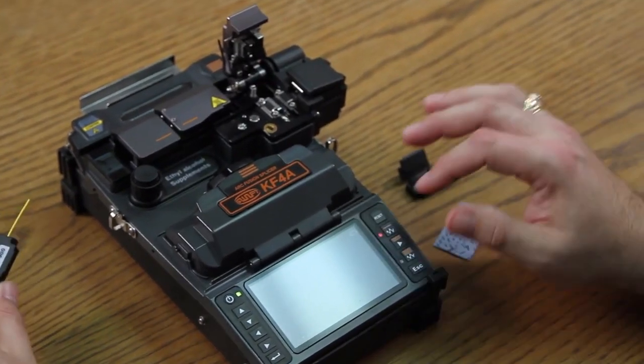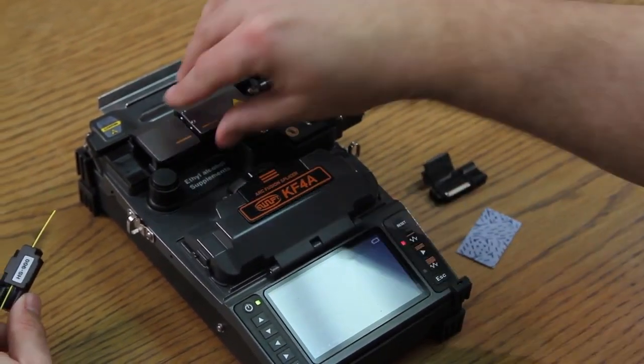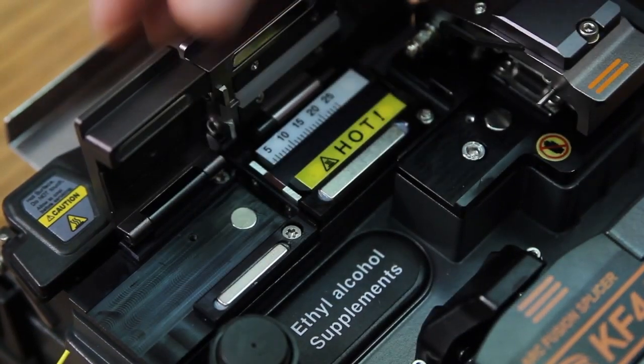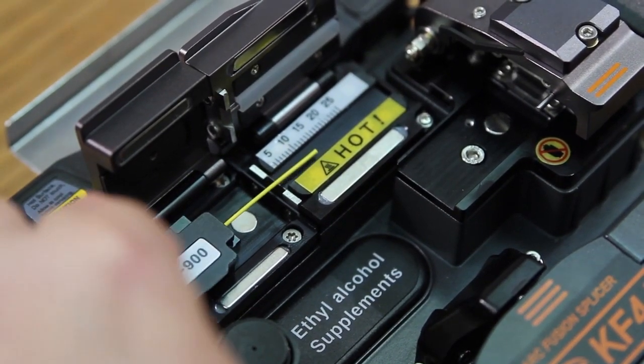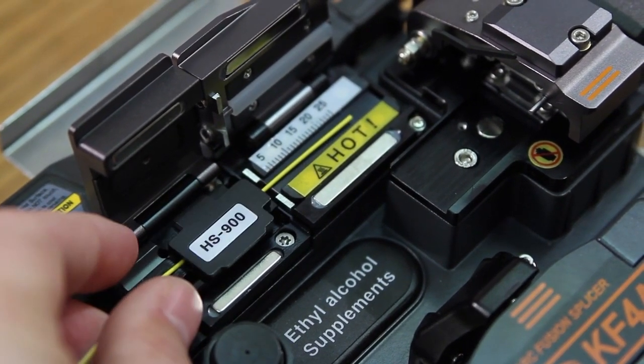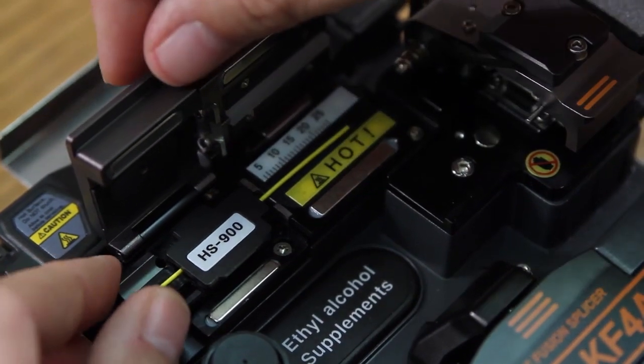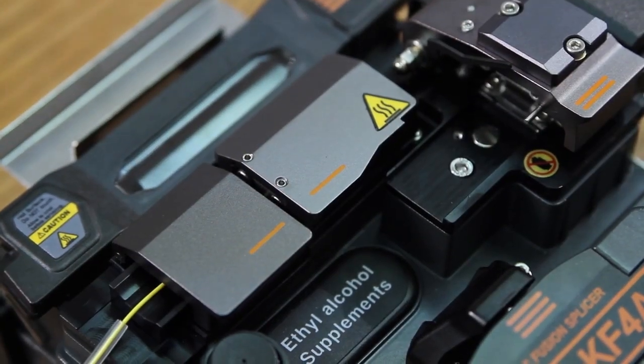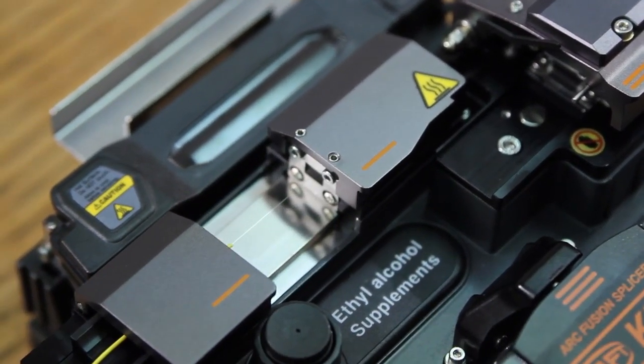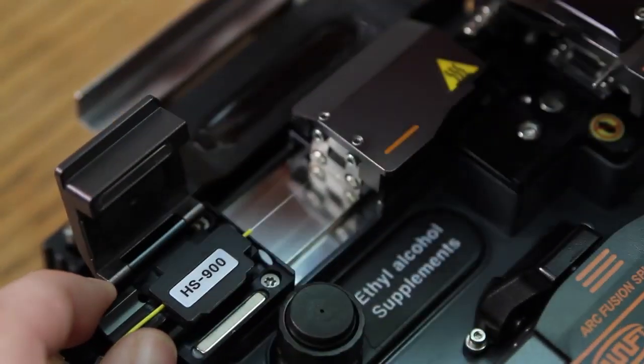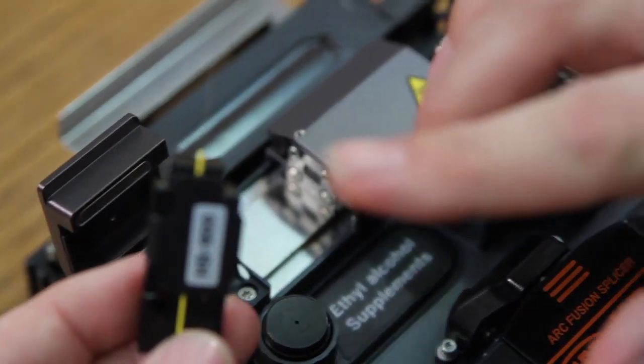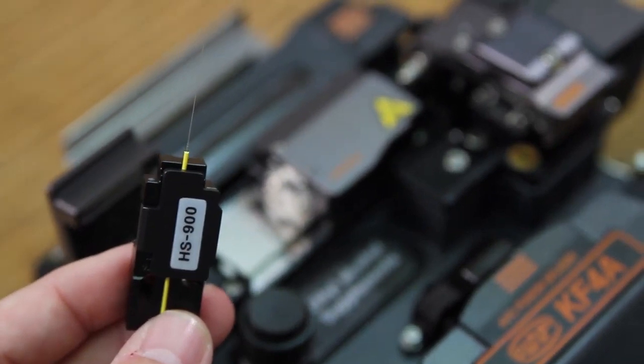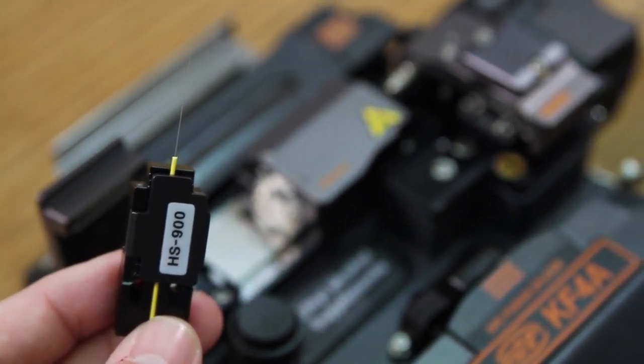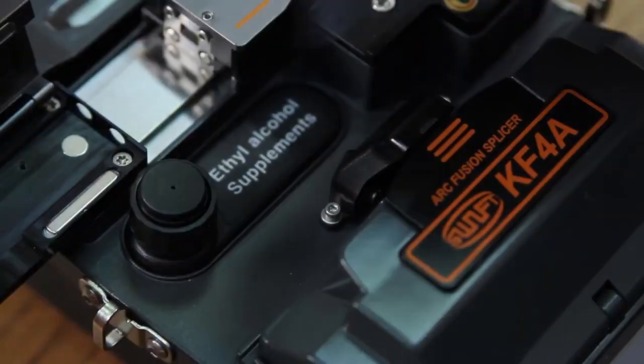Make sure your thermal stripper is turned on. Insert it into your automatic thermal stripper, making sure your holder is in the channel and closed. At this point, the stripper has removed all of the material, including the acrylate coating. Be sure to clean it before placing it into your cleaver.